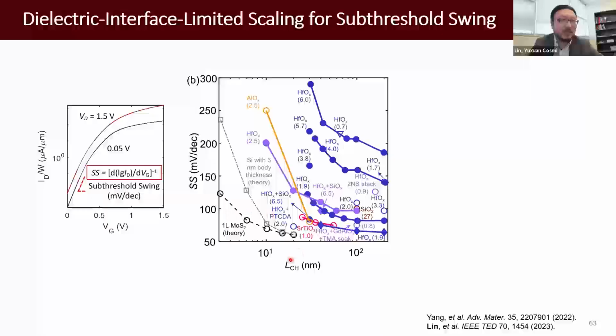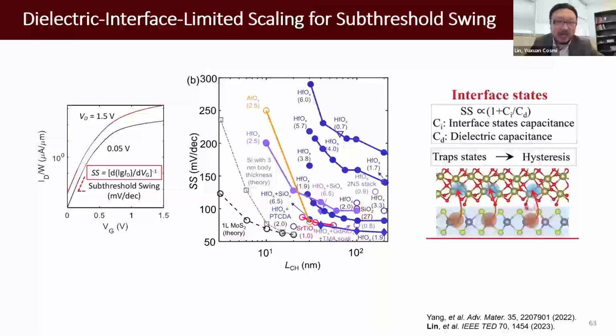are still far away. The limiting factors are actually the dangling bonds and the non-ideal interface. That gave us a lot of trap states that will make this slope less sharp. So this is another challenge we need to deal with.